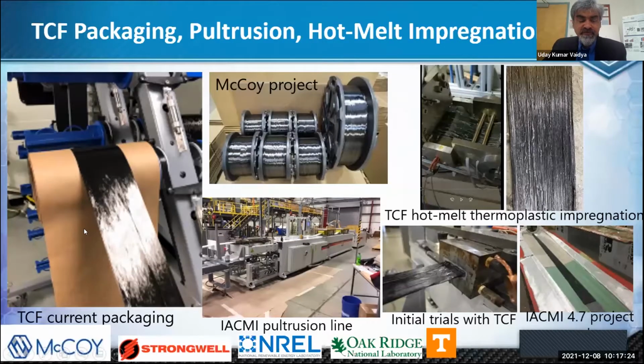One of the challenges with TCF, as some of you know from before, has been that it was packed in a brown paper packing to separate each layer from the next. Obviously this was not only expensive, but actually resulted in a lot of complications during processing at rapid speed. So we had to come up with a spooling strategy where you would not require that brown paper wrap. One of the IACMI projects looked at this, with McCoy as a partner, on a spooling strategy. We also looked at other things which I'll go through slide by slide, but this forms the continuous fiber portfolio within TCF, that is spooled fiber, pultruded, hot melt impregnated, and vacuum infused, for example.